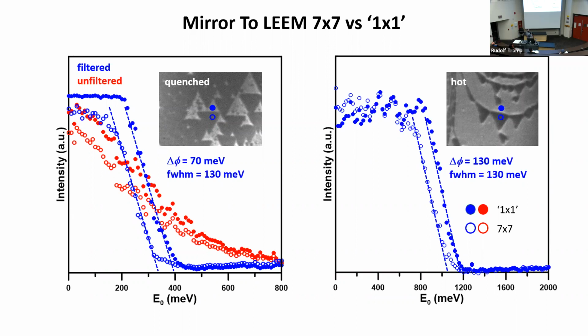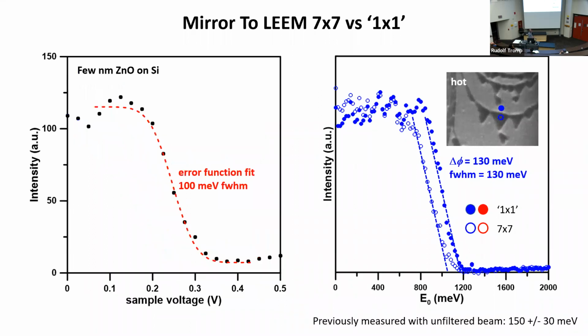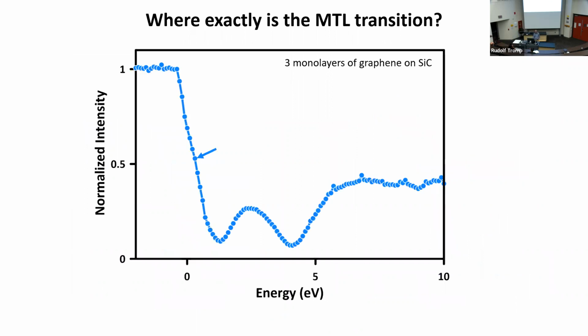So you see that this experiment went from a very sluggish, poorly resolved broad distribution to something that's much narrower. When I changed the energy filter slit from 1 micrometer to half a micrometer, I can make this even sharper. You see this fit here is an error function. There's the Gaussian energy distribution on the gun, and we get a full width half max of about 100 millivolts. Now, why is this important?